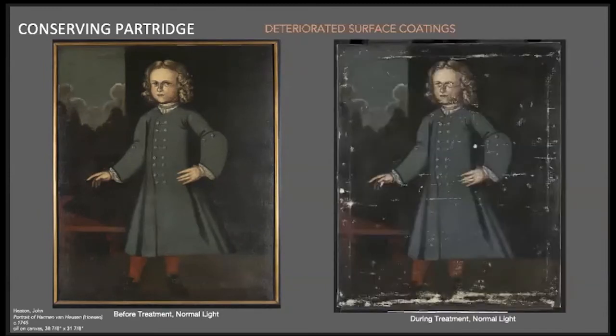Here's the same painting before and after varnish reduction. While abrasion to the paint along the margins where the stretcher or strainer is nested is common in paintings, this painting was in the worst condition out of all the paintings in the collection that came through the lab. The most significant condition issue is the abrasion seen in the areas above the sitter's hand.